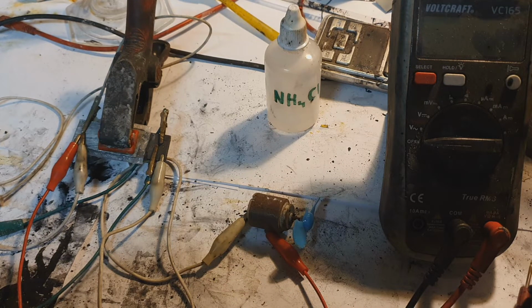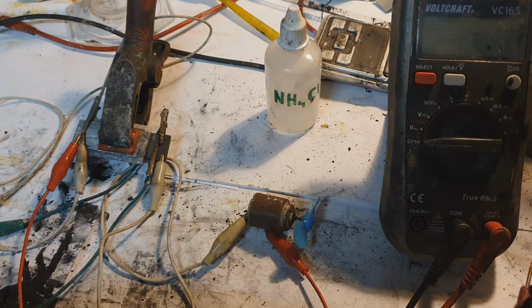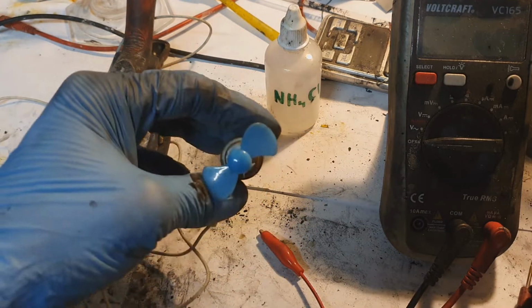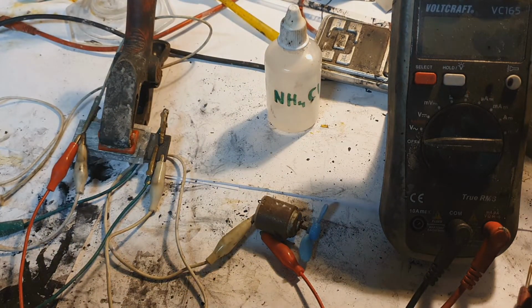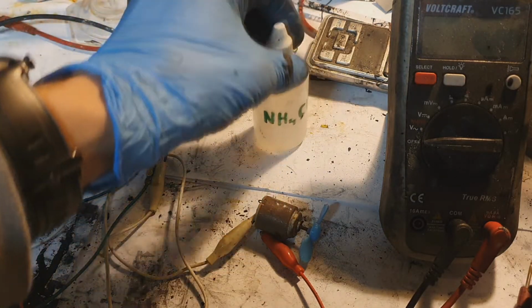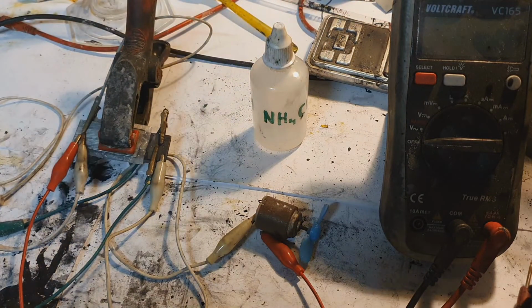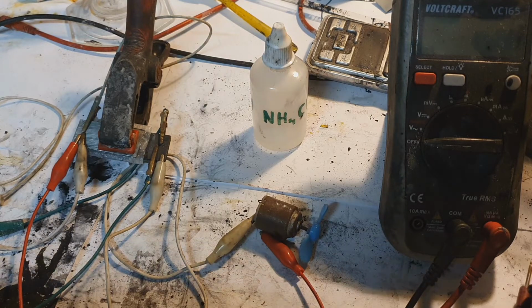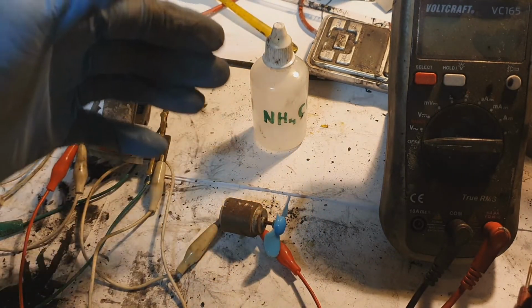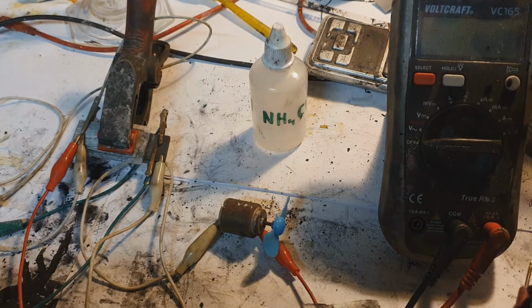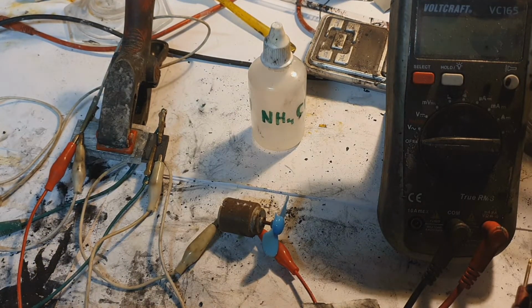For the second electrolyte, I use only zinc sulfate. The zinc sulfate was a little bit better. With zinc sulfate, I get the voltage of 1.7 volts. And the cell was able to run this motor for 10 seconds, which is really nice. So basically, I get a little bit of improvement. Then I made the third electrolyte. The third electrolyte was made from 2 mol of zinc sulfate and several drops of ammonium chloride. And at this stage I get 1.9 volts, and the motor spins for about 30 seconds, something like this. And that's it about the electrolytes for now, because I get really nice improvement.